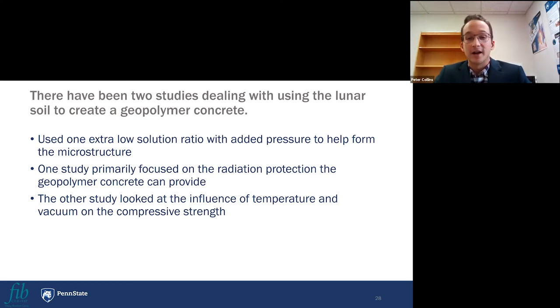As far as other work that's been done on creating a geopolymer concrete, there's really only two studies that have been done, and they used one type of solution, and it was an extra low solution ratio. So your solution to binder ratio is, I think they went clear down to about 0.2. And when you have a ratio that low, you don't get a nice workable paste. And so once it's mixed, you have to add extra pressure to help it consolidate and polymerize. We are going a different route right now. We're just trying to achieve workable paste and not do the added pressure necessarily.